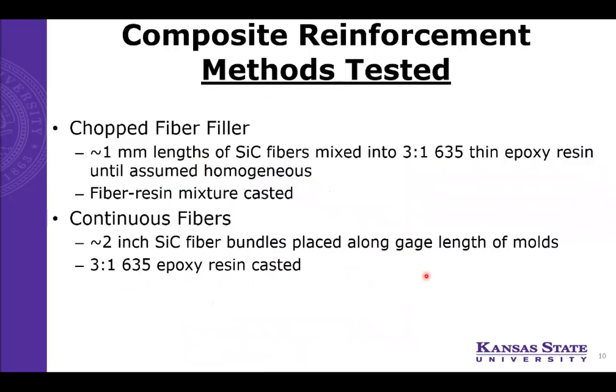So to perform our project, we had different reinforcement methods. We used chopped fiber filler and continuous fibers. To do this, for our chopped fibers, we used 1 millimeter lengths that we then mixed into our epoxy resin. And with the continuous fibers, we cut off 2-inch fiber bundles and placed those along the gauge lengths of our molds before casting the resin in our mold.